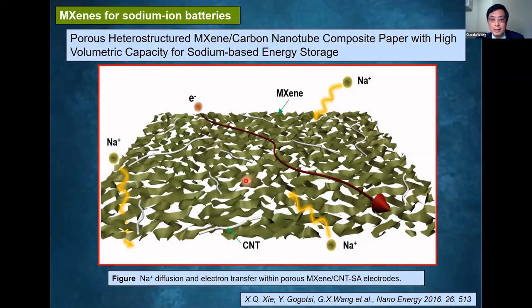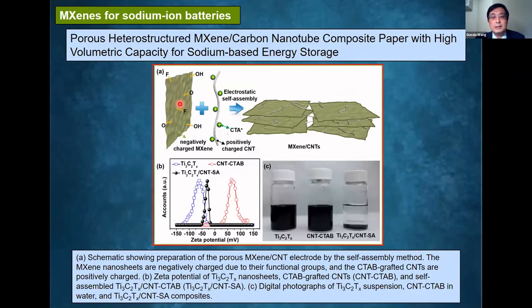So this work was done by Xiuqiang Xie. He spent 1 year visiting study in Yuri's group. He very smartly prepared MXene carbon nanotube composite paper with high volumetric capacity for sodium-based energy storage. This is the preparation process. Basically, the MXene nanosheets are negatively charged, and then we use CTAB surfactant to make carbon nanotubes positively charged, and then we can self-assemble MXene nanosheets and carbon nanotubes.